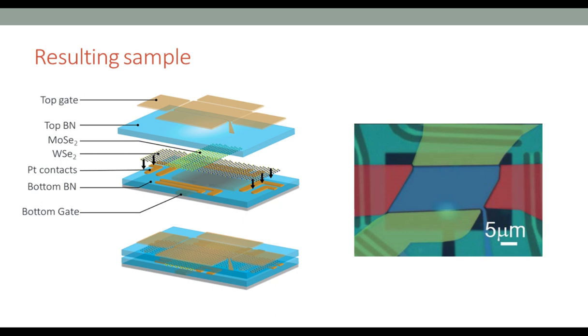So this is the resulting sample. On the right is an optical image. The green areas are the MoSe2, the red areas are the WSe2, and the blue areas are the heterostructure. And you can see that we have our top gate and bottom gate, and this actually allows us to control the electrostatics of our device.